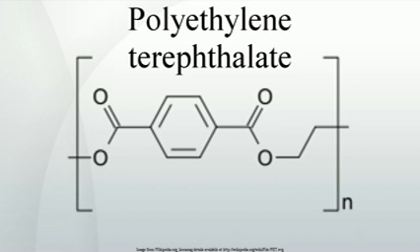Total glycolysis, methanolysis, and hydrolysis. The treatment of polyester waste through total glycolysis to fully convert the polyester to bis(2-hydroxyethyl) terephthalate, C6H4(CO2CH2CH2OH)2. This compound is purified by vacuum distillation, and is one of the intermediates used in polyester manufacture, see production. The reaction involved is as follows. This recycling route has been executed on an industrial scale in Japan as experimental production.